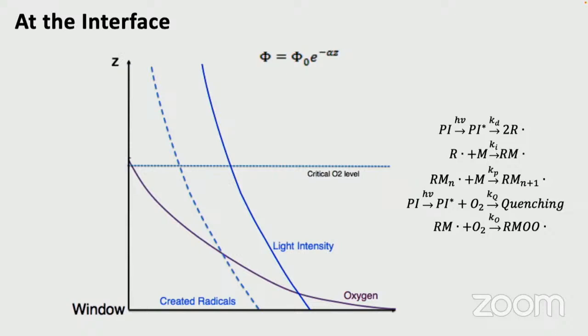So when light comes in, this is a concentration axis, general terminology, and this is a z-axis, so we're going from the window up into the liquid. Light's coming through the window. It's most intense as it enters the vat, and then the light intensity depletes with distance up into the liquid just due to molar absorptivity. That light is decomposing the photoinitiator, which generates a radical pair, so the radical concentration is highest at the window, but so is the oxygen concentration.